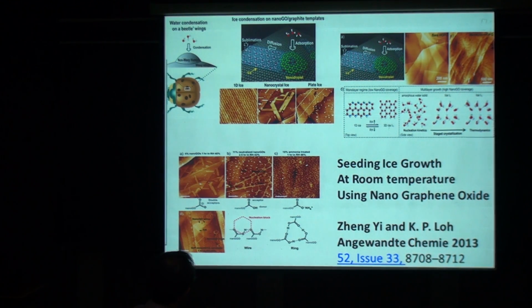Graphite is hydrophobic. Everybody knows graphite is hydrophobic. It doesn't like water. And can you grow ice on graphite at room temperature? It's probably very difficult. What we do is we seed the graphite with a little bit of graphene oxide, very small, nanoscale graphene oxide. Just sprinkle a little bit of nanoscale graphene oxide on graphite, and you'll find that it's able to condense water. You form a one-dimensional ice, you get nanocrystal ice.